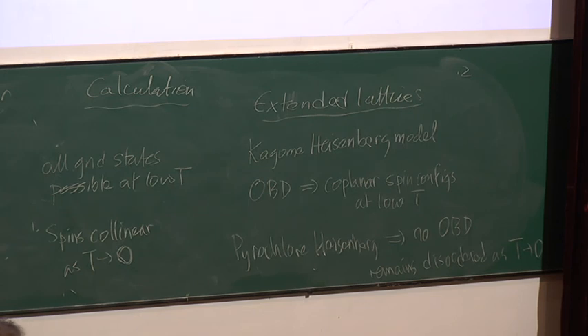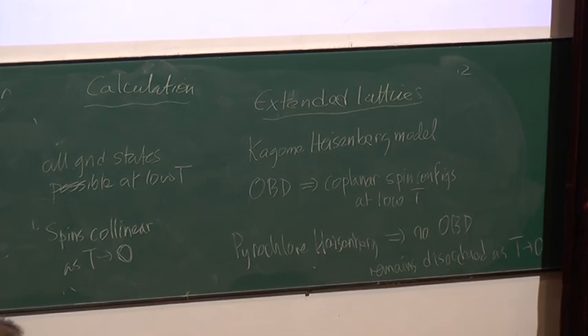As you approach 0 temperature, it develops order. You need to ask how you introduce a measure over the classical ground states. One obvious way is to take the Boltzmann measure in the limit temperature goes to 0. If that's how you do it, then you select ordered ground states. But you could construct a different measure, and there are lots of ground states which don't have this kind of order. So here essentially t tending to 0 is not the same as t equals 0.